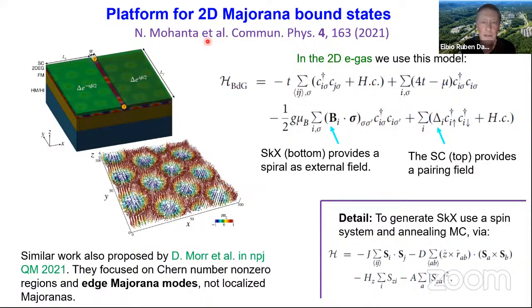And then in this recent publication, and also there is a paper by Dirk Morr in npj Quantum Materials in parallel, we have set up a two-dimensional structure where, it's a bit complicated to go through all the details, but essentially think of it as you have a lower layer that has the skyrmion crystal. Then you have a middle layer that is the one that will be influenced by the bottom and the top. The middle layer is a 2D electron gas. At the top, we place a superconductor. And in this particular geometry, we have carved a little 1D channel in the superconductor.